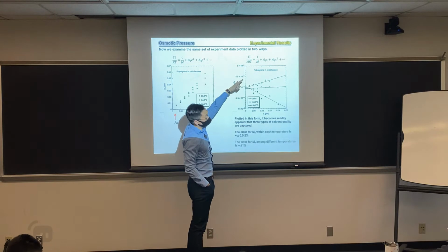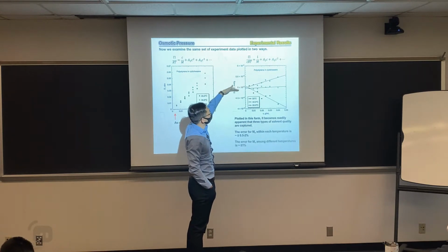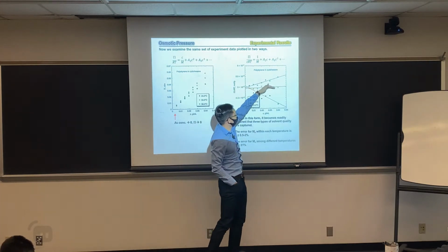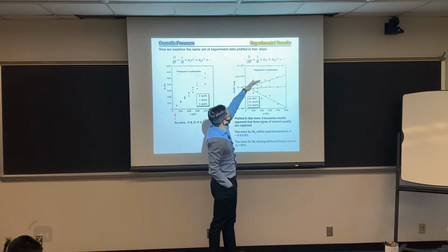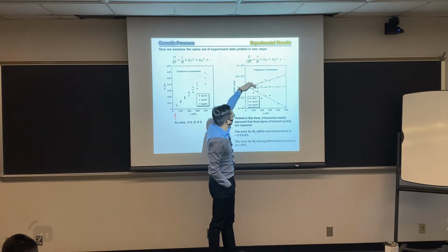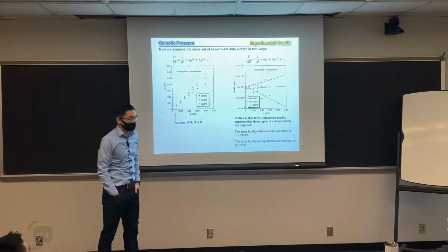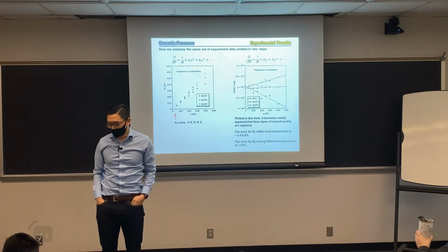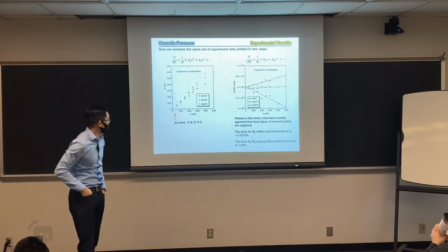Now, A2 will tell you the quality of solvents. When A2 is equal to 0 or almost flat, that means it's a Theta solvent. If A2 is a positive value, that means you have a good solvent. A2 equals a negative value means your solvent quality is not good. So that's the beauty of osmotic pressure, how you can use it for determining the quality of solvent.